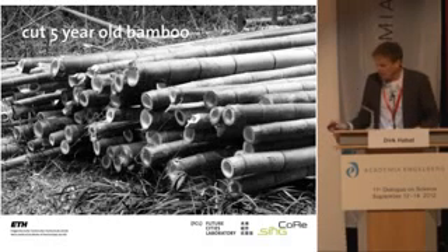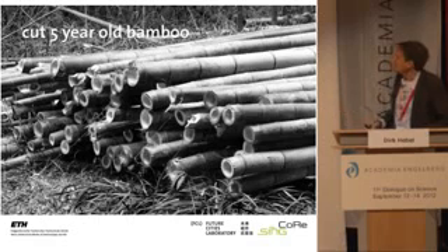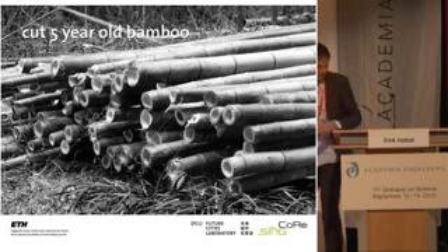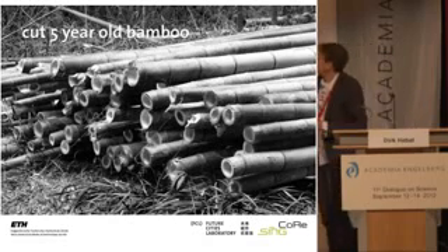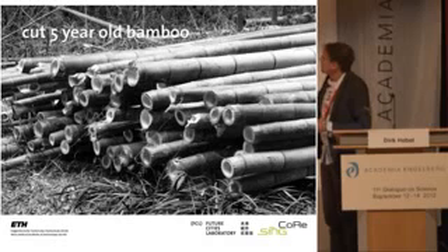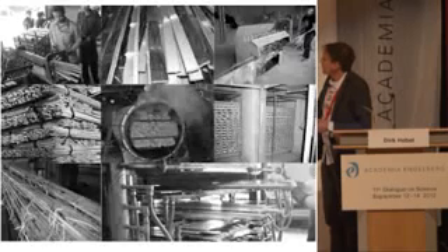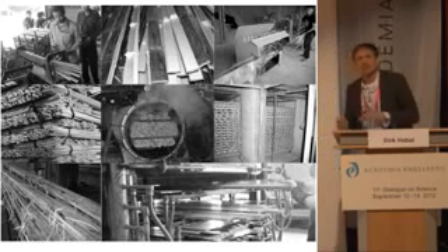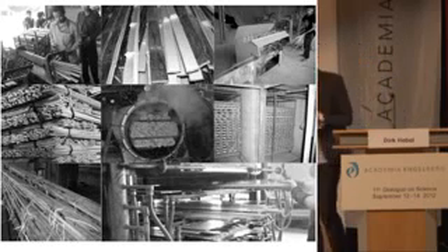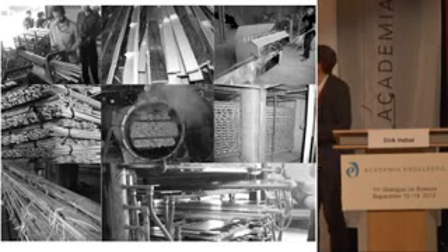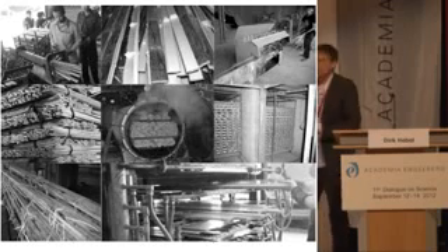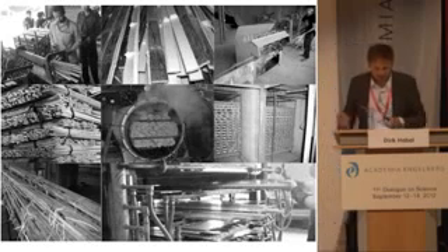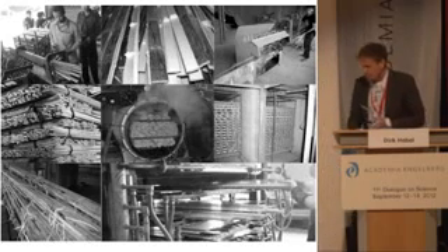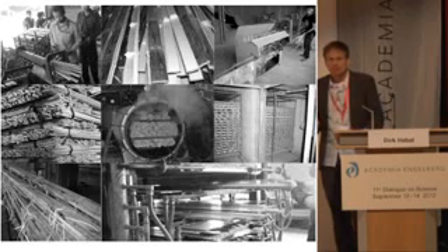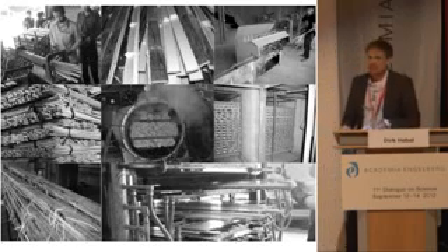So the idea is that when you harvest this material, the bamboo as a raw material, you basically start, and you see it in the upper left image, you start to split it into even smaller pieces. You boil or carbonize it to get the sugar out of it, so it is not attractive anymore to bacteria, because bacteria and insects like the sugar usually in these organic materials. You dry it again, then you mix it together with the glue, and then in a so-called hot press, you press the material together. And the big advantage of that material being mixed with a glue or with an adhesive is that it is water resistant.